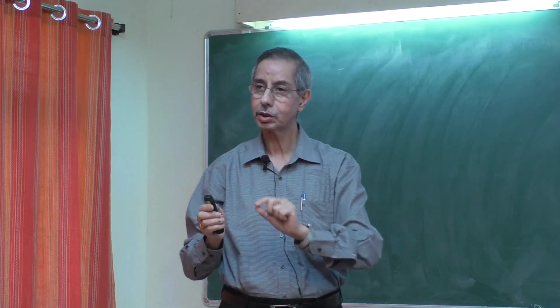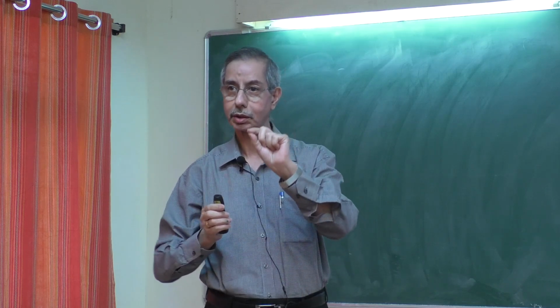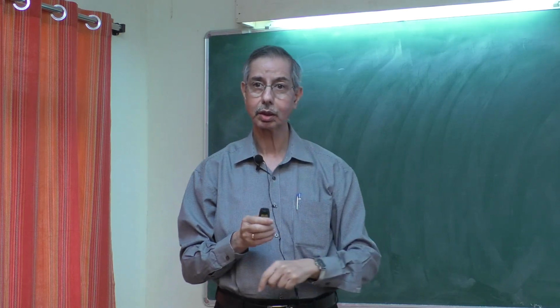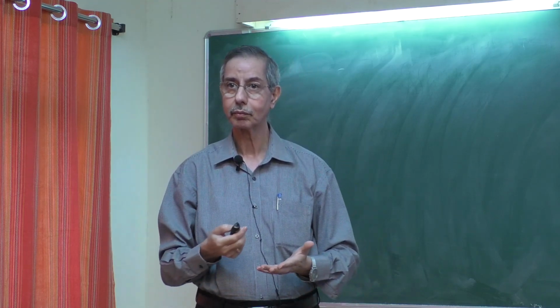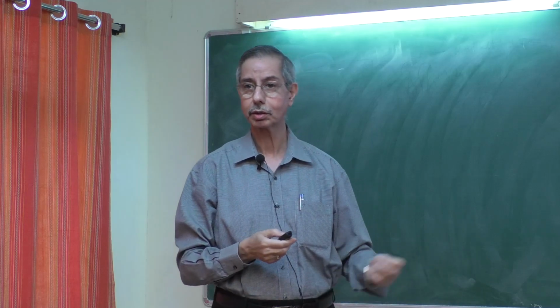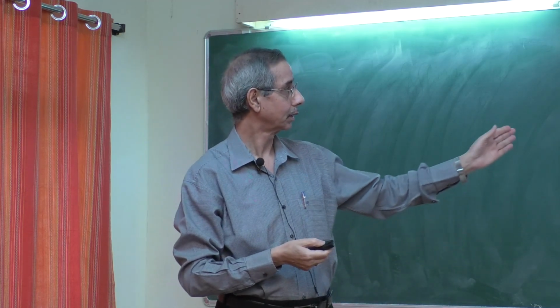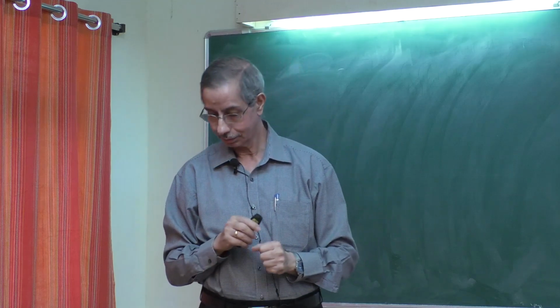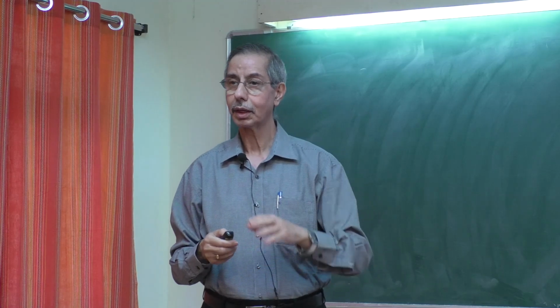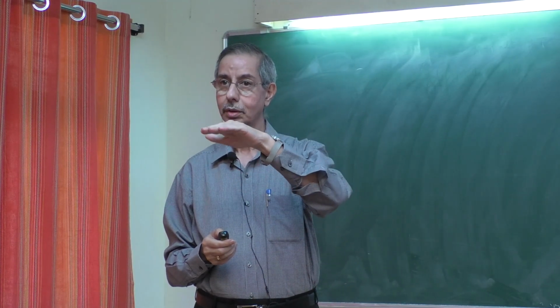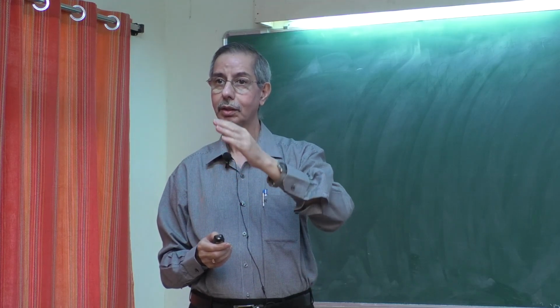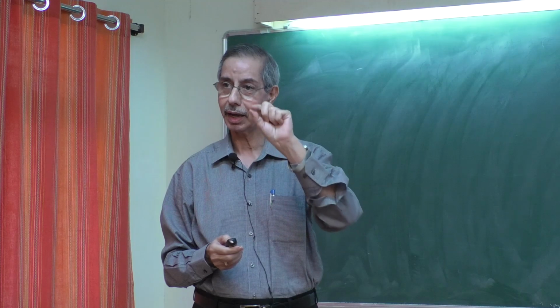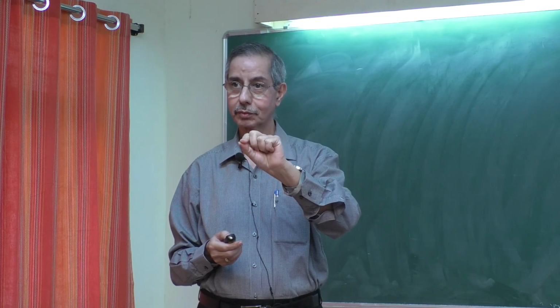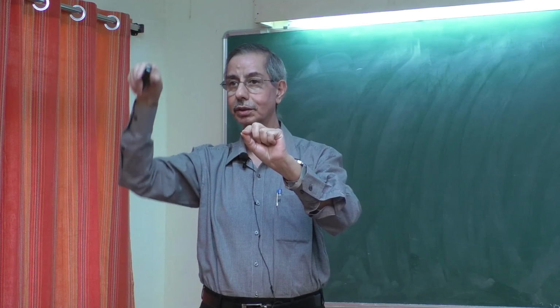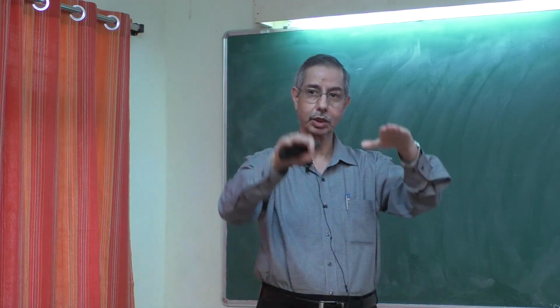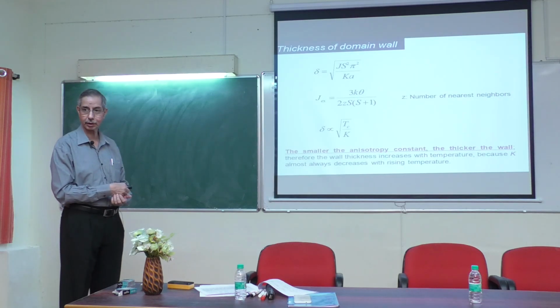So exchange energy would increase a little bit, the anisotropy energy would increase a little bit, but the decrease in the magnetostatic energy is huge, a factor of 2. So two domain configuration would be preferred over single domain, and the division into different domains will go on occurring as long as the energy cost that you have to pay for creating these different domain walls, in terms of the exchange energy and anisotropy energy, is balanced by a corresponding reduction in the magnetostatic energy. When this trade-off takes place, delta, the width of the wall, is proportional to 1 by root k.